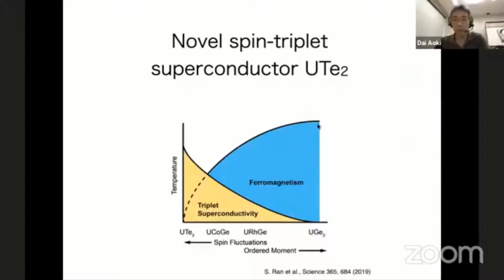This material was first discovered by Sheng Ran in the NIST group, the Nick Butch group. In their paper, they show this schematic figure of temperature versus ordered moment or spin fluctuation. Uranium germanium 2, uranium rhodium germanium, and uranium cobalt germanium are located here because they show ferromagnetic order, a ferromagnetic state, and then superconductivity appears. Uranium ditelluride is believed to be at the verge of ferromagnetic order, but it doesn't show ferromagnetism. But I want to say that it's not very simple in this material, so I want to explain in more detail.